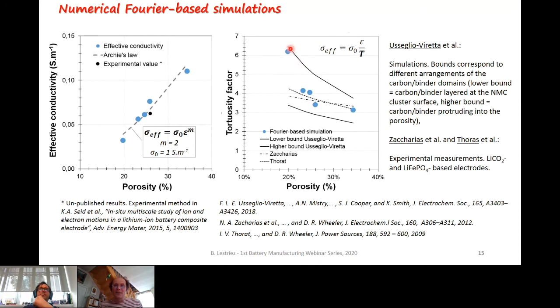The first ones were obtained by Usseglio-Viretta and other speakers this week, Mistry and Cooper. So our results are in between their two bounds. Their bounds, if I remember well, were obtained by numerical simulations on electrode architectures that were reconstructed from X-ray tomography, with the CB-PVDF domains mathematically generated with two hypotheses. For the lower bound, the CB-PVDF domains were distributed as layers at the surface of the NMC clusters, while for the higher bound, these domains are more protruding into the porosity. So our results are in between these two bounds.